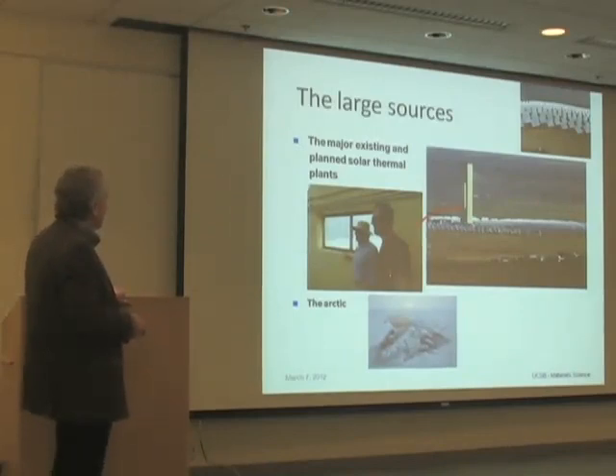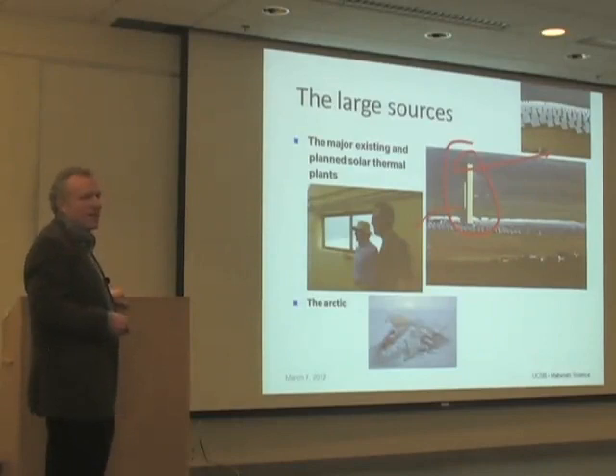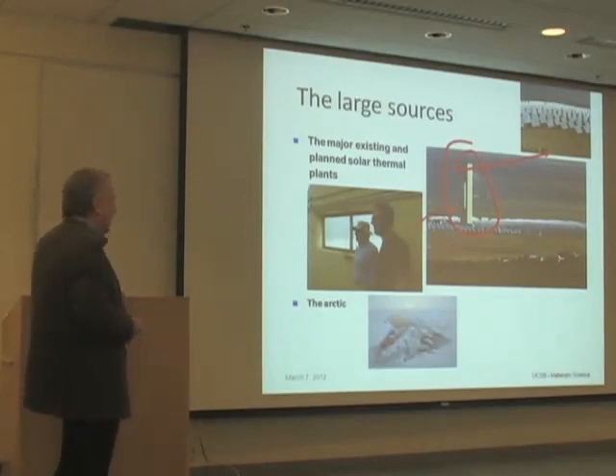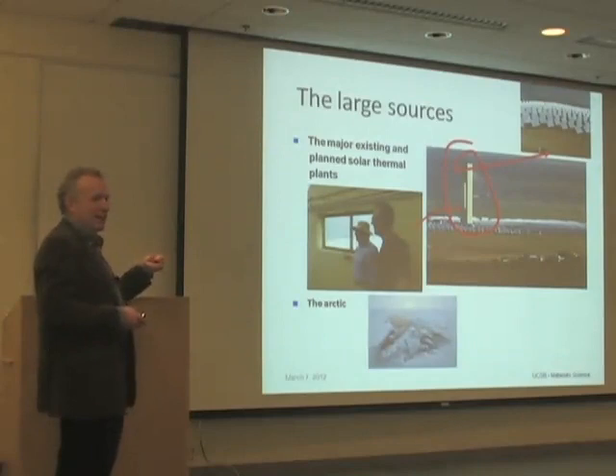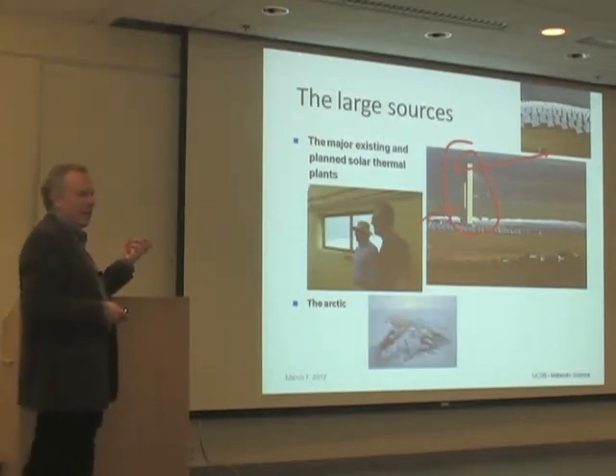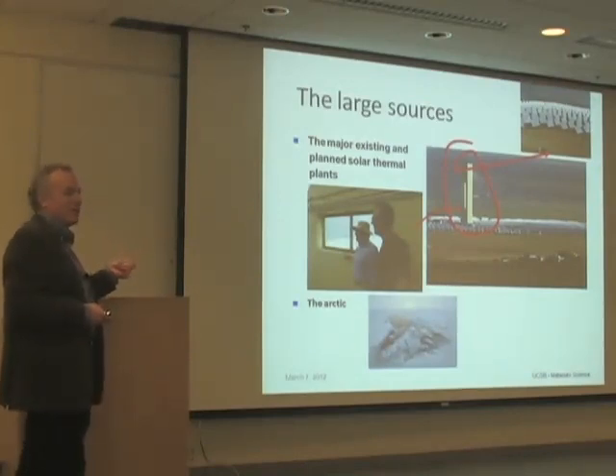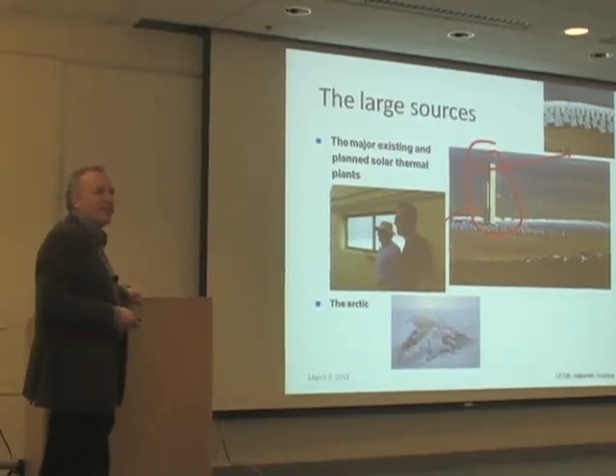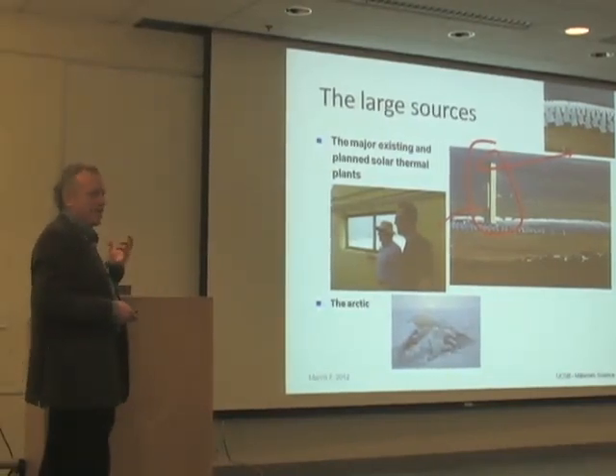So the point is, with a material like I've been discussing, it seems like you don't need that tower. And you don't need all that infrastructure. You don't need those heat exchangers and those boilers and all those piping systems, because you can have the material at the focal point of your mirror, and you need a shuttering device to change the temperature. But potentially, it's a very compact energy conversion device that requires no fluids and no pumping around.